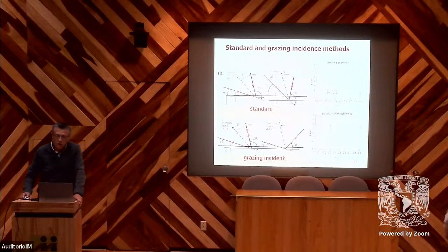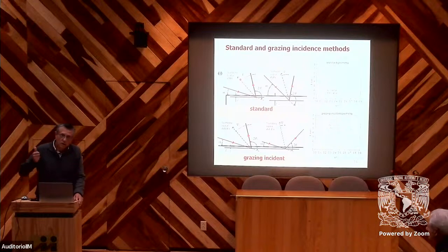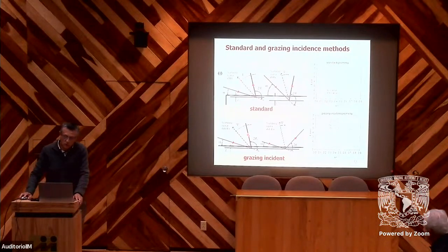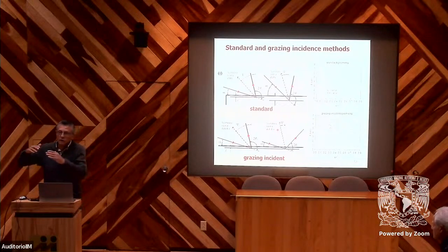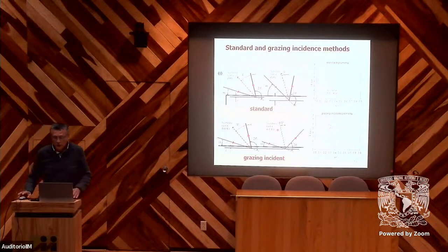And for grazing incidence, this is more firm. This is a more constant incidence angle, and the tilt is obtained by using different reflections. That means in this case, you use only one HKL, it's the same. So the calculation is very simple because you use only one elastic constant. That means you can have linear correlations also, so mathematically it's easy. But this here is more complicated because you use different HKL. That means it's like if you use different approaches with different initial numbers. But the advantage is that if you use constant alpha, you have relatively constant penetration as a function of psi angle. And if you change the angle, you change the penetration.